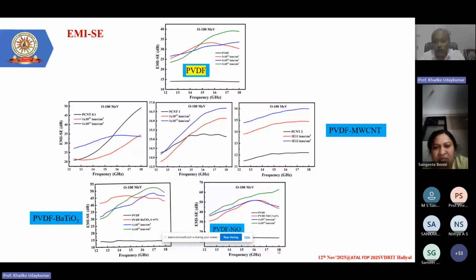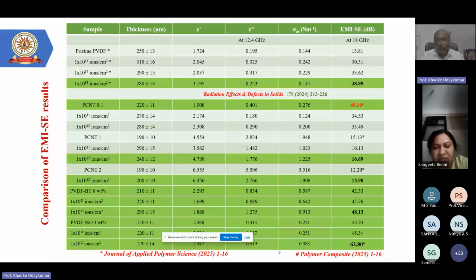So this is the message I thought of just mentioning. These are the complete details that I am showing. When the oxygen beam is used with pure PVDF, it gives a maximum of 38.89. Carbon nanotube with PVDF unirradiated gives 49.1, but after irradiation, it has drastically reduced. Then these are all reduced when you are taking carbon nanotube.